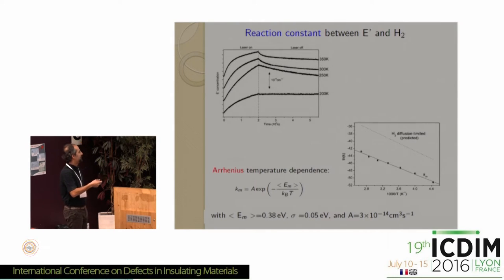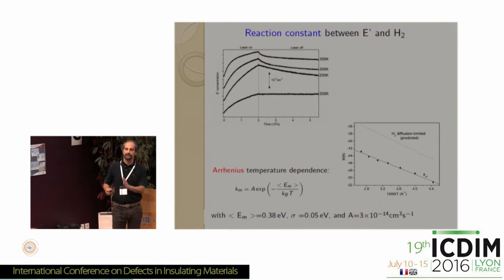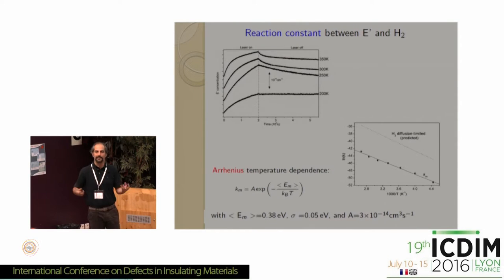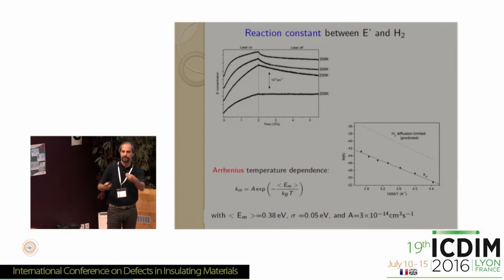One interesting thing that we found is that the activation energy of this reaction is statistically distributed. You cannot reproduce the kinetics unless you assume that there is some statistical distribution of the energy required for the reaction. And this is a manifestation of the disordered nature of the system, which gives rise to fluctuation from center to center of the activation energy needed for the reaction with hydrogen.